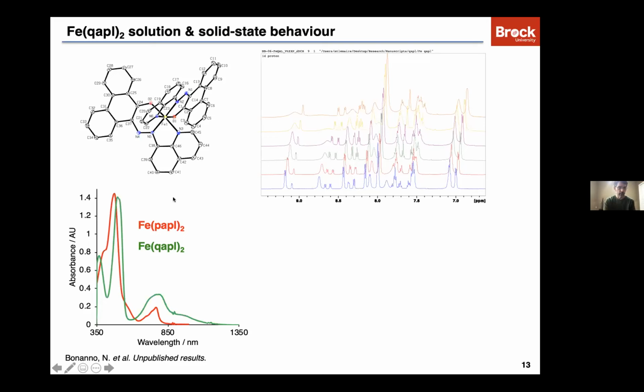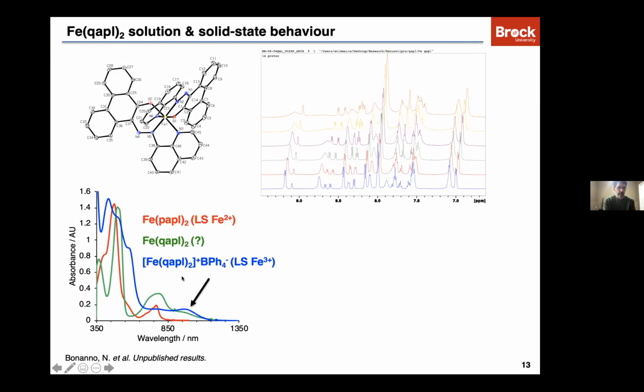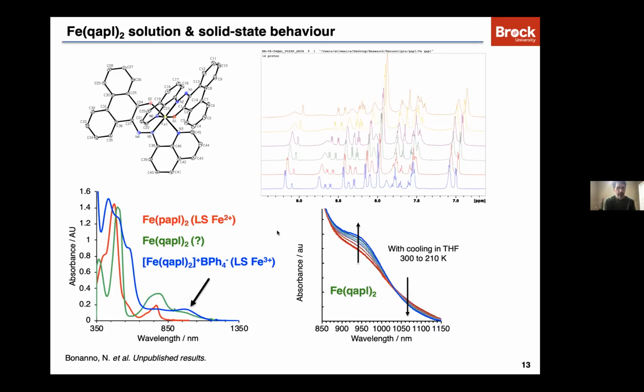Well, if we look at the UV visible spectrum, we compare the QAPL complex to the iron PAPL complex, we see roughly similar features, except in the QAPL complex, we have this very low energy shoulder, and we deliberately made an iron 3 complex by oxidation of this iron QAPL complex. And if you compare the UV visible spectra of the iron QAPL parent complex and then the oxidized complex, we see this feature in the oxidized complex as well. In the iron QAPL complex that's not oxidized, there's a temperature dependence.